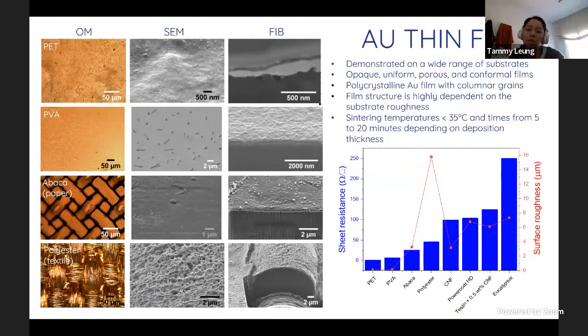Firstly, for the gold film, we were able to deposit successfully on a wide range of substrates, ranging from the typical polymers, papers, and fabric, which resulted in different types of opaque gold films. These films themselves varied in roughness depending on the substrate that they were first deposited on. So it could go from very smooth to extremely rough, as the roughness is carried on from the substrate below. The films could be sintered for as little as 5 minutes for a very thin film, or up to 20 minutes in order to obtain an optimal, highly conductive film.